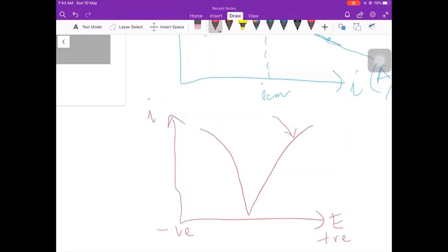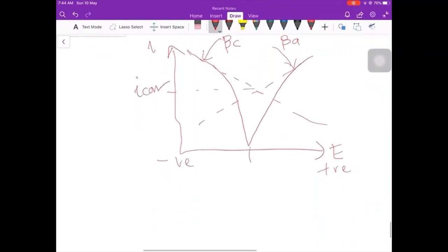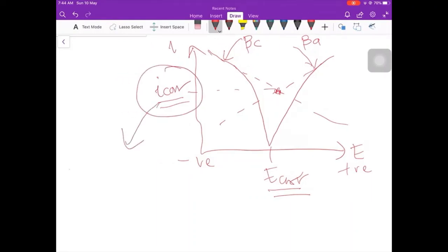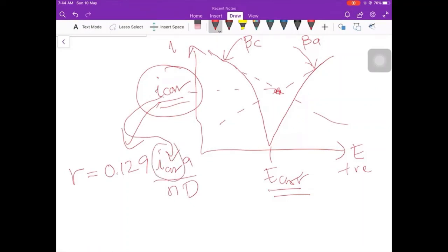Okay, this is the positive direction, this is the negative direction, so this is beta A. This is beta C. You can cross here. So this is the value for I corr, and this is E corr. Corrosion current density and corrosion potential. This corrosion potential, this is corrosion current density. This value is very important to know the corrosion rate. R is the corrosion rate. You can put I corr in this equation.